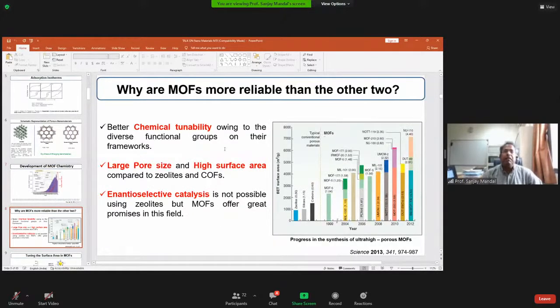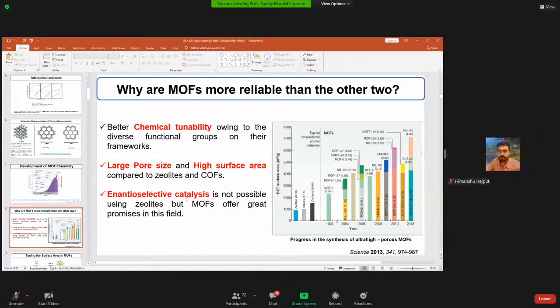Why? Because compared to the other two materials, zeolite and COF, you can have chemical tunability. In zeolite you have the pore size fixed, but here, as I will show you, you can tune the pore size, and you can also get high surface area. On the other hand, enantioselective catalysis is only possible with MOFs, not by zeolite.